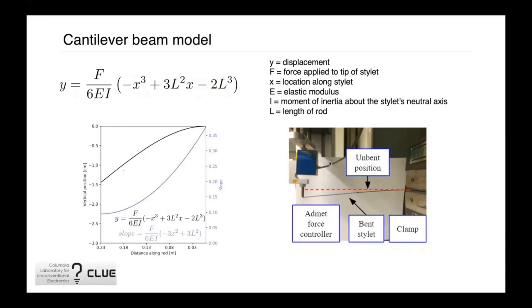So for example, with a bending condition of 0.1 newtons of force placed at the tip, we see that the stylet bends on the left side of the graph. What's more important to highlight is that the slope of the stylet is greatest near the base end of the rod. So this means that by placing the strain gauges at the base end, we can provide the maximum amount of bending induced strain. Also, placing the strain gauges at this location limits contact of the strain gauges with any brain tissue, since the device is to remain outside of the brain throughout the entire surgical procedure.